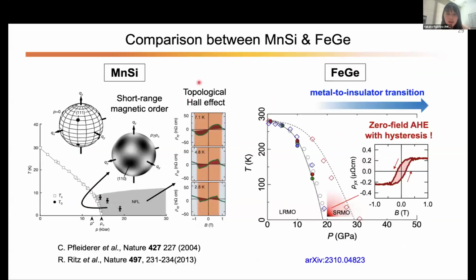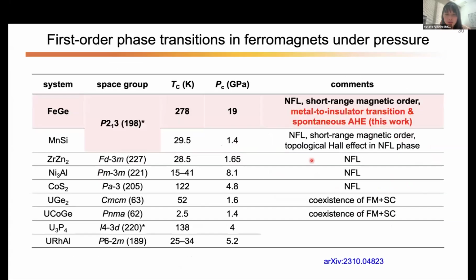So finally, I would like to compare the result between the manganese silicide and this time our material, iron germanium. In manganese silicide, they observe a field-induced topological Hall effect, which suggests the possible liquid state of the magnetic skyrmion. But in iron germanium, we observed a very unusual time reversal symmetry breaking in this short range magnetic order state, which is dominated by the chiral fluctuations.